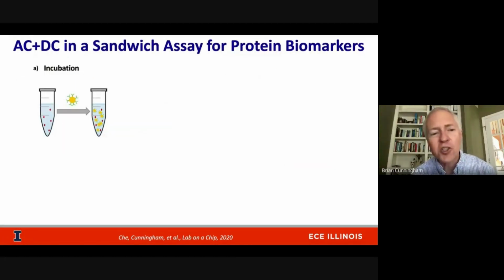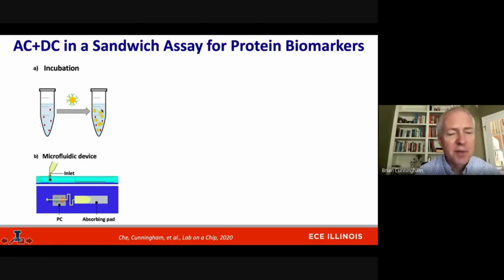We've used the same approach for doing a sandwich assay in the context of detecting a protein biomarker. So same basic idea, except we prepare our nanoparticle with a capturing antibody that we mix in a small plastic test tube with our test sample to gather a protein antigen. And then we incorporated our photonic crystal into a microfluidic device where we could take a single droplet of this test sample, put it in, and then have that test sample run over the photonic crystal while being absorbed with a little bit of slow flow through the use of an absorbing paper pad.